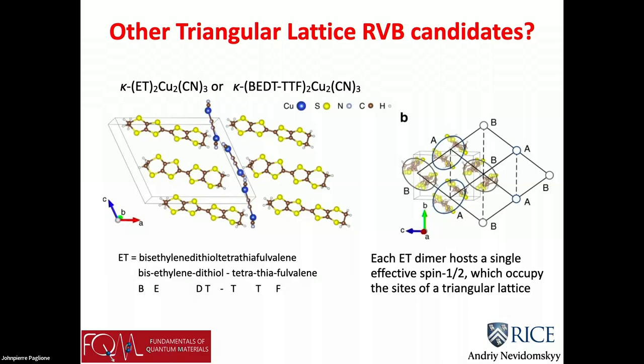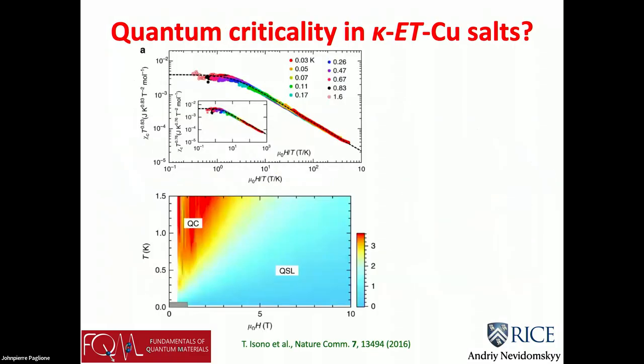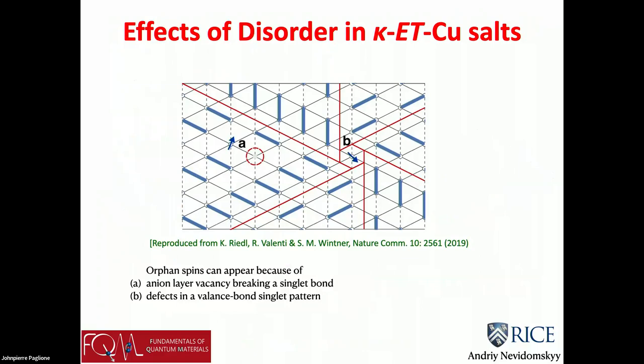And again, there is rich physics going on, where the effective spin half actually comes from two organic molecules being next to one another. It's a series of molecular orbitals. Essentially, there's one electron which is in the state of this molecular orbital, and that's the effective spin. And again, there has been a long history. There are quantum criticality suggestions, where you have certain collapse. And again, unfortunately, the disorder comes in. So, for instance, what happens often is that, again, purely chemically, you could have an anion layer vacancy.